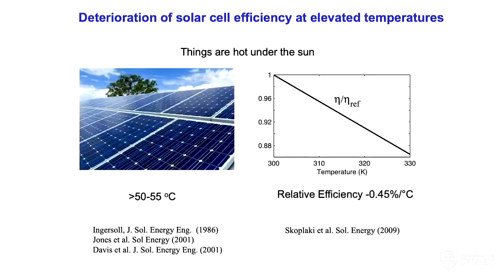So now, instead of generating color with sunlight, one of the technologically very important things about the sun is the solar cell. One thing is that things are hot under the sun, as I alluded to a few times already. A solar cell on a roof typically operates at a very high temperature because of solar heating. The typical operating temperature is about 50 to 55 degrees Celsius. Compared with a 30 degrees Celsius operating environment, that translates into more than 1 percentage point of efficiency loss for a silicon solar cell, which is a very substantial penalty.